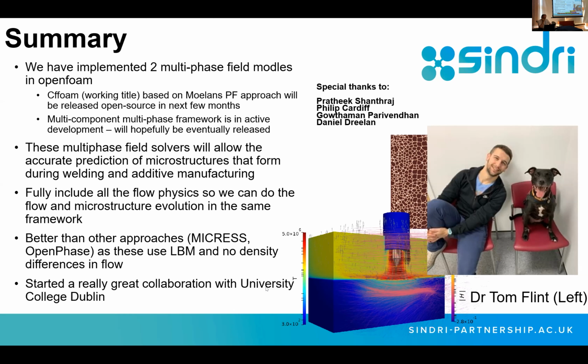Yeah, but what you could do is have one phase here, and a lot of people use a coloring function. But the trouble with that is when you include the anisotropy, you're saying that the crystal over there has an order parameter of whatever, and this one has the same. What you're saying is they have the same anisotropy, they're aligned the same. So you're introducing an artificial texture into the material.